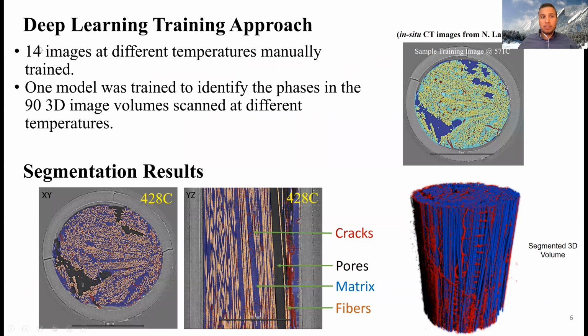So our approach for this study was to take 14 images at different temperatures and manually segment them. So as you can see here, this is a sample training image where we go through the manual labor of highlighting the fibers, the voids, the matrices, and the cracks, as you can see here in red. So after these 14 images, we trained one model to be able to identify the phases in the other 90 images. So we used 14 images to identify 180,000 images at different temperatures. And the results here, we just picked up a sample of volume that is scanned at 428 C.